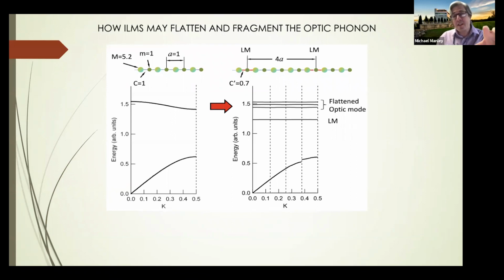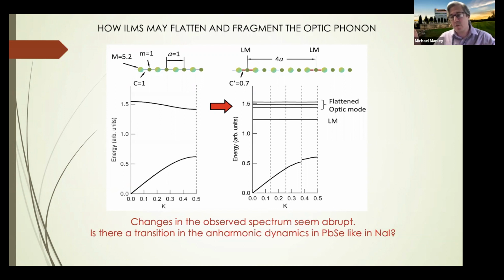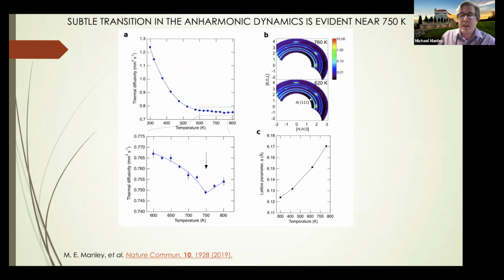The other thing, though, is that this change occurs fairly abruptly, which is something we'd seen before. In sodium iodide, there are transitions where they order into different states, so the local modes will form patterns. We wanted to see if anything was happening there, and we know that we could pick them up. It tends to be subtle. It's not like a structural change. And we keep track of the structure at the same time, by the way.